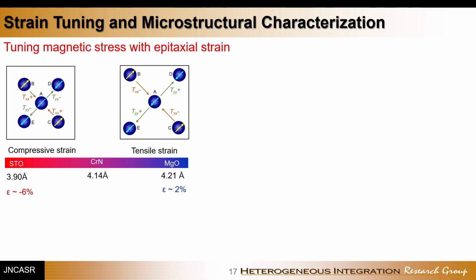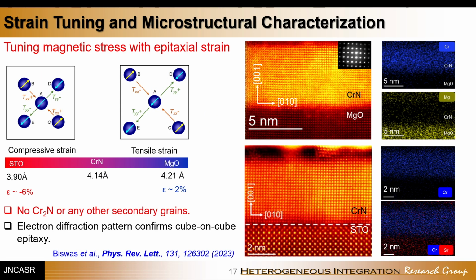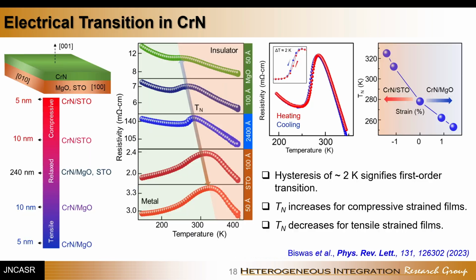So what we did is that we deposited chromium nitride on 2 substrates, in one case STO, the strontium titanate, and in one case MgO. In one case, we apply a compressive stress. In the other case, we apply a tensile stress. And then we grow this film as a very thin layer, 5 nanometer and 10 nanometer. And when you do this electrical measurement, as you can see, there's a clear trend in the shift of the MIT temperature.